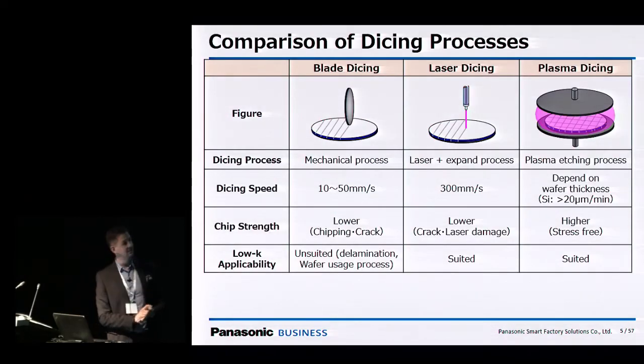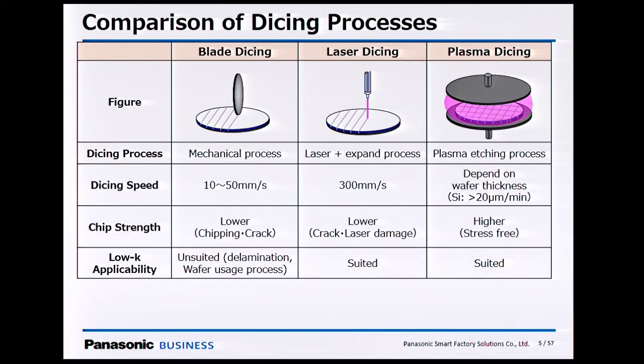So again, if we line the existing techniques up with each other, we have blade and laser dicing. As you can see, line by line. So the first thing you can think is as the devices get smaller, the length of time to dice the whole wafer will increase. That doesn't affect plasma dicing because the mask is existing on the whole wafer. The only thing that's affecting the dicing time is the thickness and the material of the wafer.